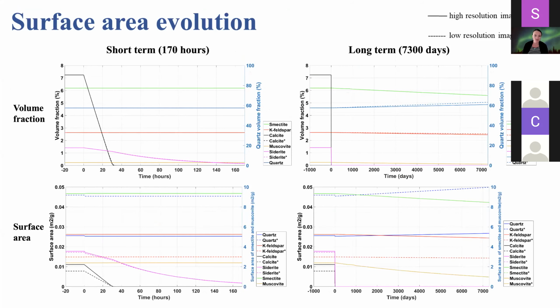In terms of the evolution of surface area, again, we have the short-term simulations on the left and the long-term on the right. We can see the evolution of surface area mimics the evolution of mineral volume fractions. So surface area starts to decrease as the volume fractions decrease. There's really little difference in the surface area evolution of the two simulations.